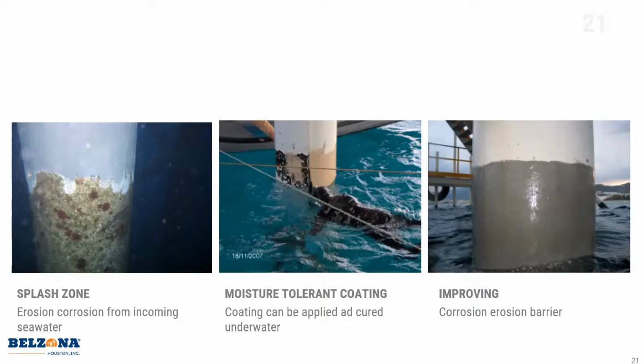So this coating has hydrophobic properties where you can mix it, go underwater, and I've seen it on the paintbrush and it just does not come off. So it does not mix with water. Put it right on the substrate and it will wet out the substrate and stay on the substrate. And even with waves and stuff, it does not get splashed away. So believe it or not, we can coat things underwater.